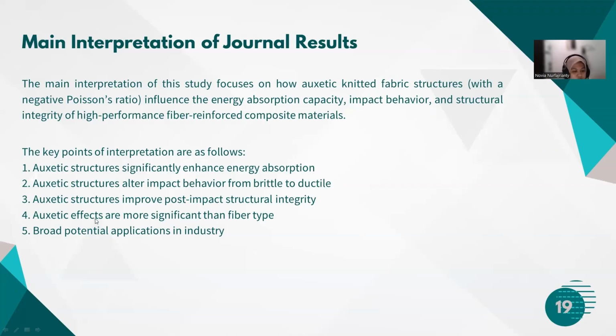Auxetic effects are more significant than fiber type. Both pure para-aramid fiber and hybrid fiber saw similar performance improvements when combined with auxetic structures. Even though the hybrid fiber had lower stiffness, the geometric effect of the auxetic structure still provided high energy absorption. This demonstrates that textile structure design is equally important or even more important than fiber selection in the development of high-performance composites. And then, broad potential application in industry.